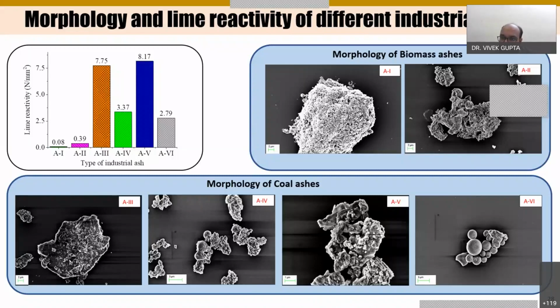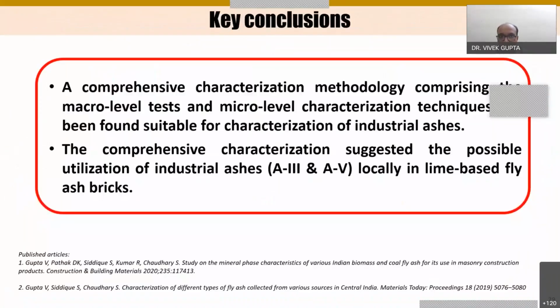And you can note down that in the concrete, when we are preparing the flowable mix, then we prefer the spherical particles of the ashes. But when we are going for the compressed bricks or the unfired bricks, as such we do not require the slump flow. We generally use the low moist mix for the casting of the bricks. So as such the angular characteristics of the ashes are not detrimental to the properties of the fly ash bricks. And we can see that probably the angular characteristics have resulted in the better lime reactivity of the ashes. So these are the key conclusions from this particular part of the study, like a comprehensive characterization methodology